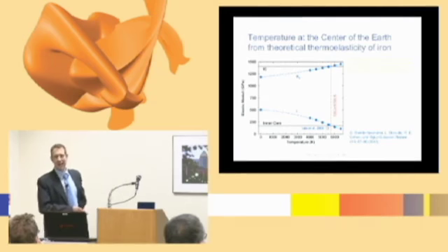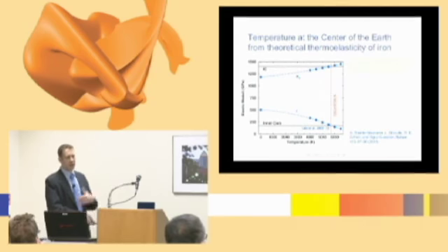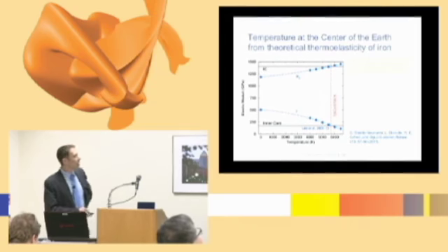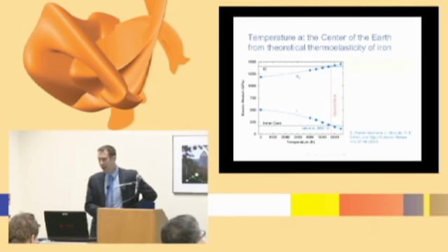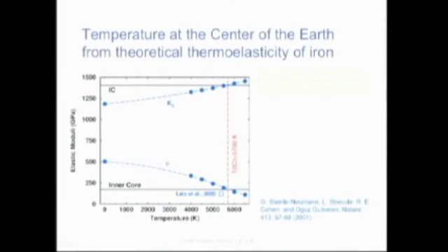Now, seismology is not so sensitive to the shear modulus in the inner core of the Earth, because the inner core of the Earth is surrounded by a liquid outer core which does not support shear waves. But using a combination of seismology and free oscillation studies, there are some quite accurate estimates of the elastic moduli of Earth's inner core, which is believed to consist of iron. So we calculated the shear and bulk sound velocities and moduli of iron as a function of temperature, and ended up with a temperature of about 6,000 Kelvin, which is probably the best estimate we have of what that important